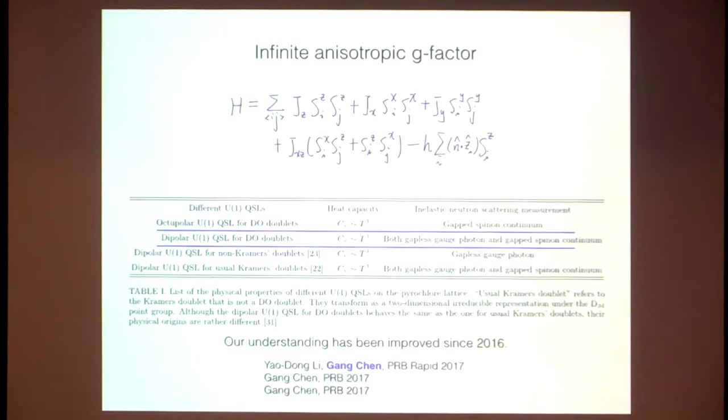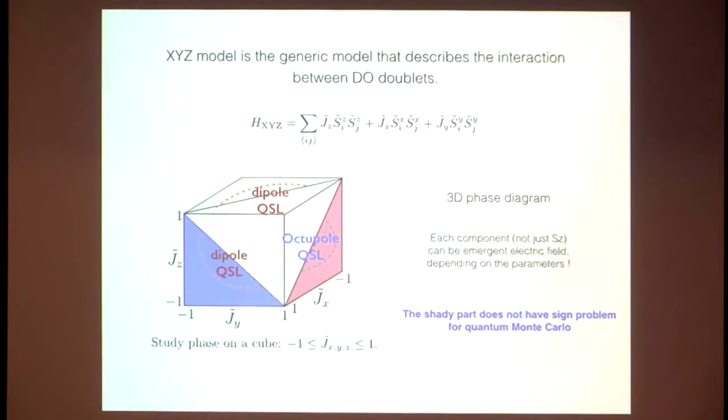Similarly, neutron scattering will also couple to and observe the Sz correlation function. One can try to figure out what neutron scattering actually measures. Imagine in this corner where the Jz component is dominant, and Sz would be the quantization axis for your problem.